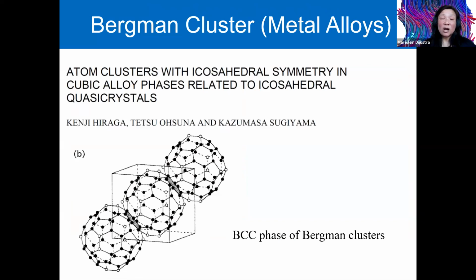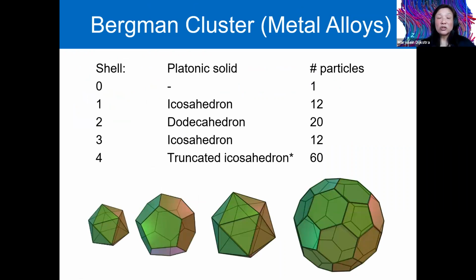The Bergman clusters are already known to play a major role in the formation of icosahedral quasicrystals. These Bergman clusters consist of a single sphere in the center. Then there's an icosahedral layer of 12 spheres around it. Then there's a second layer of 20 spheres in a dodecahedral fashion. Then there are 12 spheres around it in an icosahedral fashion. And then around that, there are 60 particles in a truncated icosahedral fashion, which is basically the soccer ball.